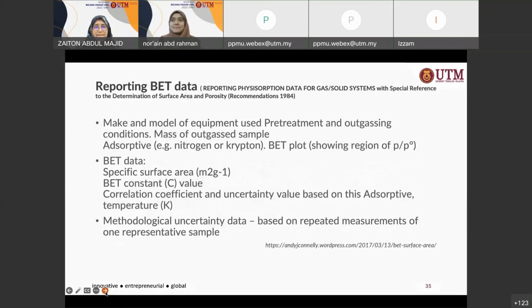Okay, and then how do you report your BET surface area data? Make sure that when you report your BET data, this is taken from the report, "Reporting physisorption data for gas/solid systems with special reference to the determination of surface area and porosity." Make sure you note down the model of equipment used, the pre-treatment and outgassing conditions, and the mass of the outgassed sample that you use. So note that down, because different instruments have different specifications.